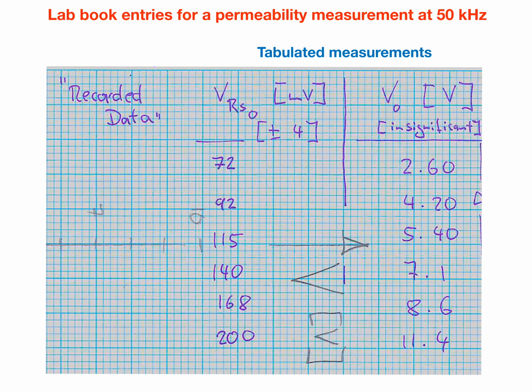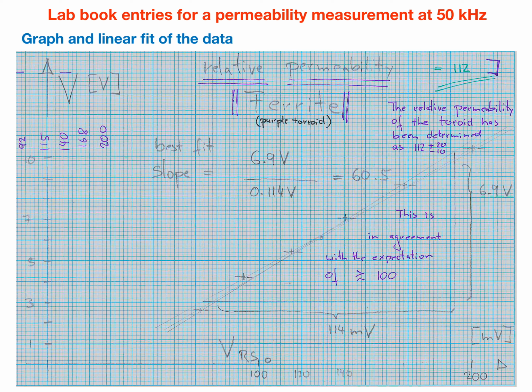They are given in volts. The graph shows V versus VRS, and it can be seen that the 6 data points follow a linear trend. The data have been fitted with a straight line, and a slope of 60.5 has been determined. Maximum and minimum estimates for this slope have also been carried out.